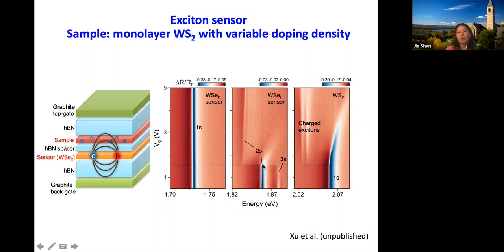Okay. So here we have a very good signature of what's going on in the sample layer. If you follow the intensity and also the energy of the 2s state, as soon as the sample changes from insulating to metallic, from incompressible to compressible, you see a redshift in the 2s energy and also a loss of oscillator strength.